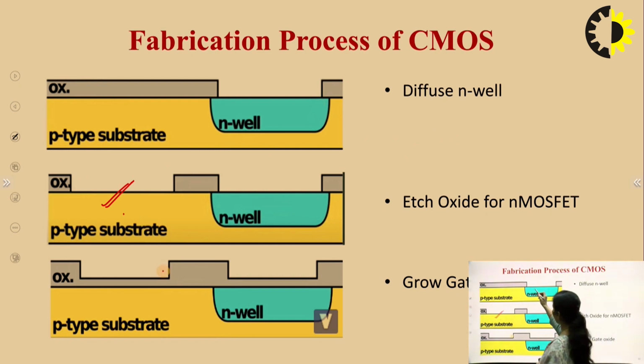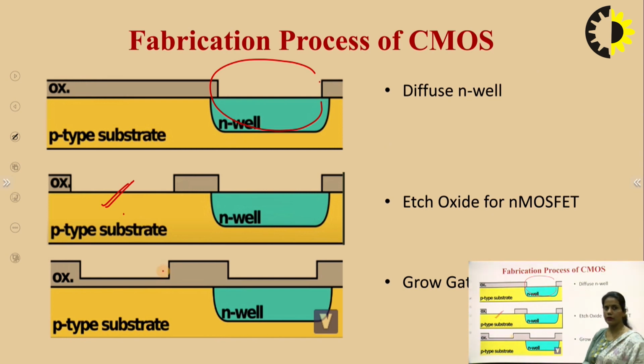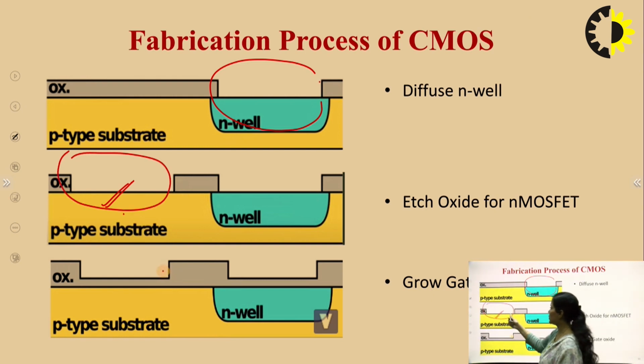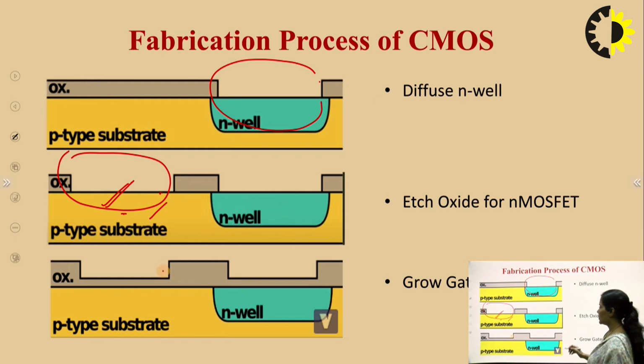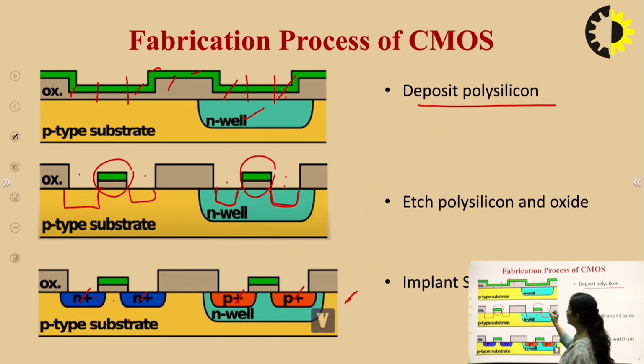So now we are left with the substrate, and we are having an open portion over here in which the N-type well has been created using diffusion process. Again, in the second patterning step, this portion has been exposed and the oxide layer has been etched, which is used for making the N MOSFET. Again, after depositing the gate oxide layer and polysilicon layer, etching is done to make the gate electrodes, and after fabricating the gate electrodes, finally the diffusion process or ion implantation is used to create the source and drain regions in both P MOSFET and N MOSFET.